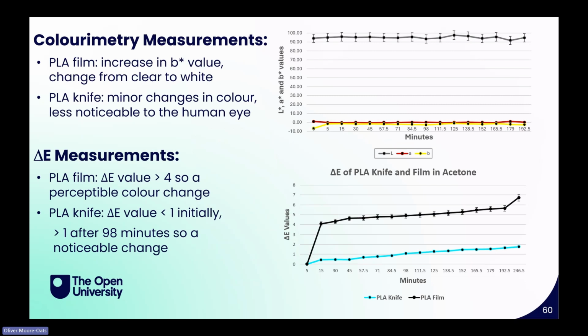So here are the measurements. In the top graph, you see our values, which are L, A, and B. What's really interesting is that the film in the 5-minute time, which became from clear to white, had an increase in the B value. However, the PLA knife had really minor changes, less than 1. And on the bottom, you can see the delta E values, how they change, and how from 0 to 5 minutes, it went above 4.